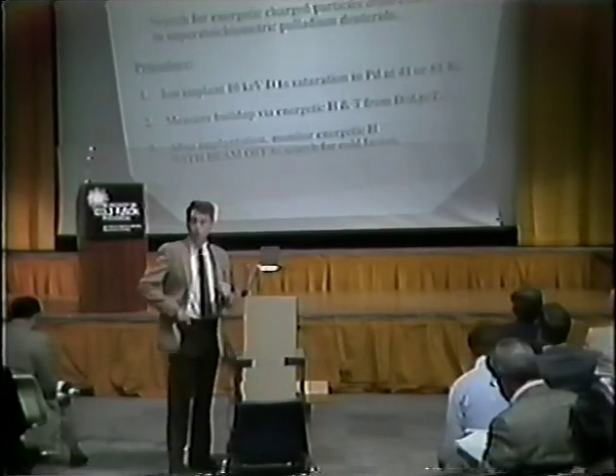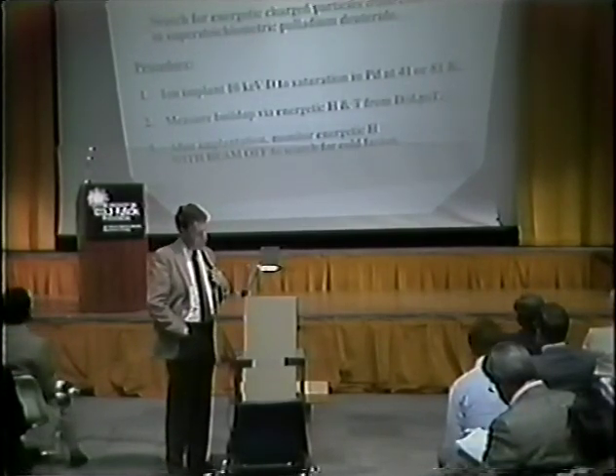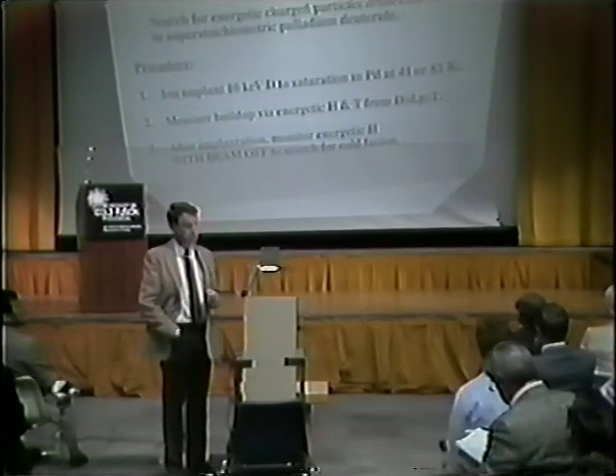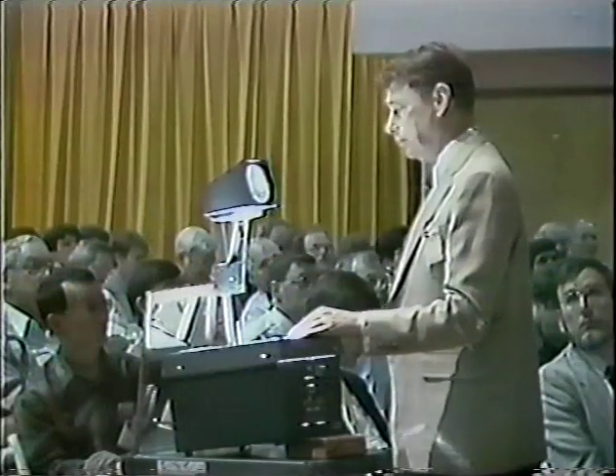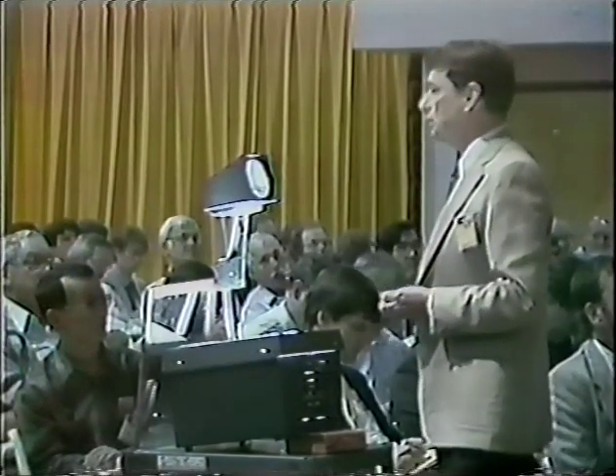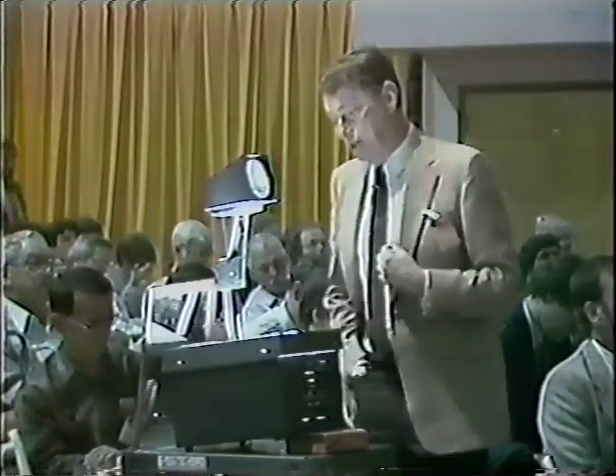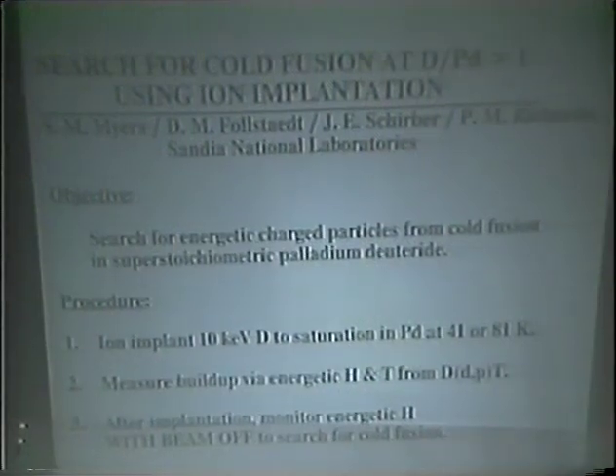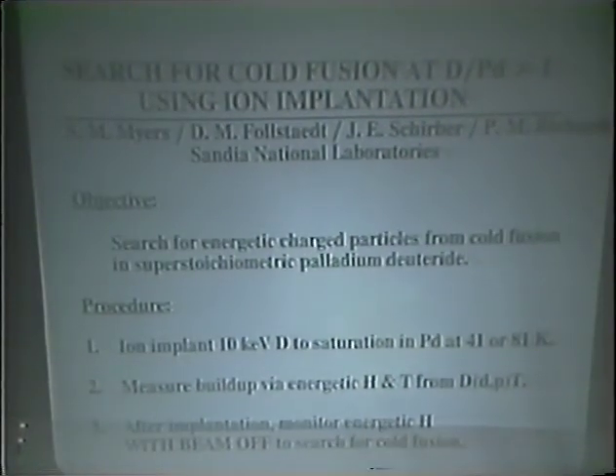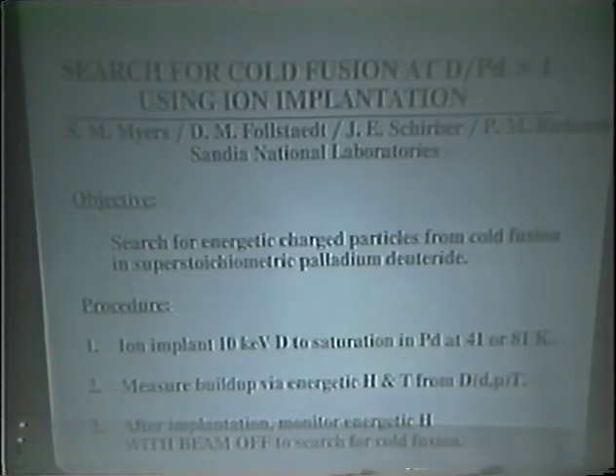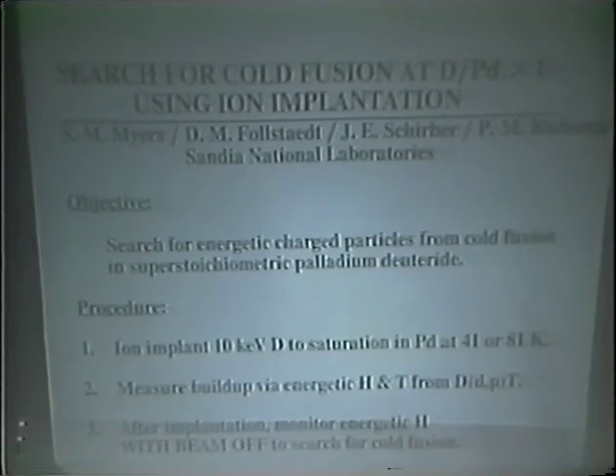Well, I'd like to discuss some experiments in which we have searched for cold fusion in palladium deuteride that was formed by ion implantation of deuterium at cryogenic temperatures. Our motivation in using this rather unconventional way of forming the deuteride was that it is capable of introducing deuterium to palladium atomic ratios substantially greater than 1.